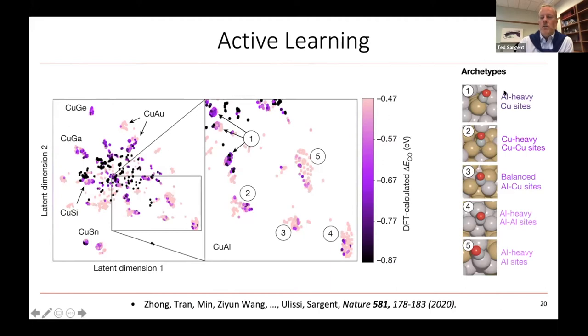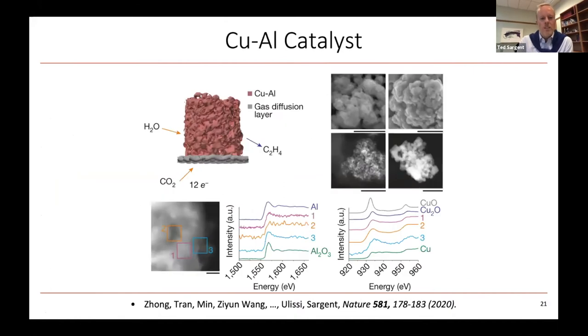And that corresponds to these aluminum heavy copper sites. And you can see that we're too weakly bound, for example, in clusters 4 and 5 typically, which are too aluminum heavy. So it also enabled us to kind of coarsely estimate a good concentration range for the aluminum, which is in the 5, 10, 15% range rather than the very, very aluminum heavy range. So that sent us into the lab.